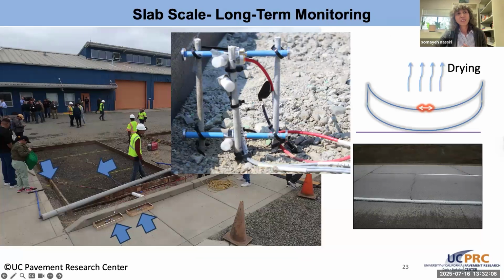So for each one of these tested slabs, we put a strong emphasis on mid-range and long-range monitoring. And in order to do that, as you can see, these trees are basically strain gauge trees, and they're blown up here, and there are relative humidity sensor and temperature sensor trees. And these beams that you can see over here, they're unrestrained drying shrinkage beams. And the goal of this is that we track drying shrinkage.